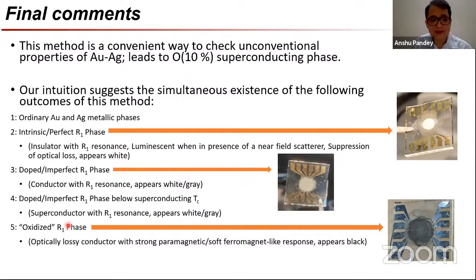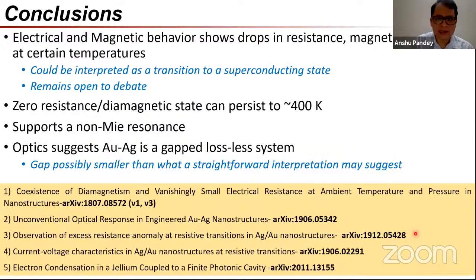And then lastly, there is the oxidized R1 phase, where all we see is now some form of a conductor, which is quite optically lossy. It's extremely dark in appearance. And on the occasions when we have tried to measure its magnetic properties, we found it's a paramagnet or a soft ferromagnet, which we don't understand because gold should not be. So with that, I'll conclude.